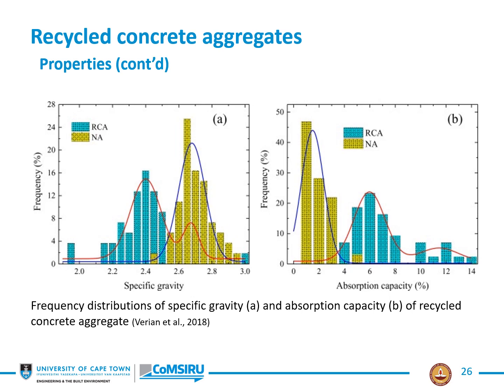This is also illustrated here where we have these frequency plots of recycled aggregate versus natural aggregate. And in the specific gravity or relative density plot, obviously the natural aggregate has higher relative density, whereas the recycled aggregate lower. And the other picture in terms of absorption. Here, the natural aggregate has low absorption, the recycled aggregate has relatively high absorption.